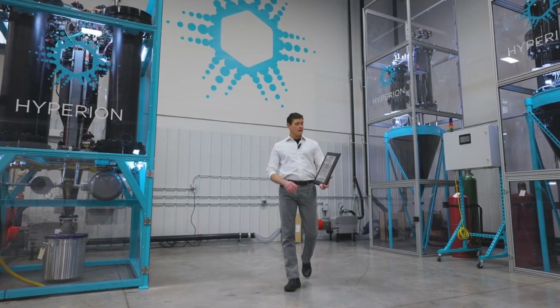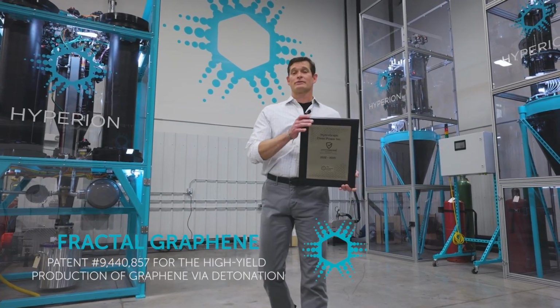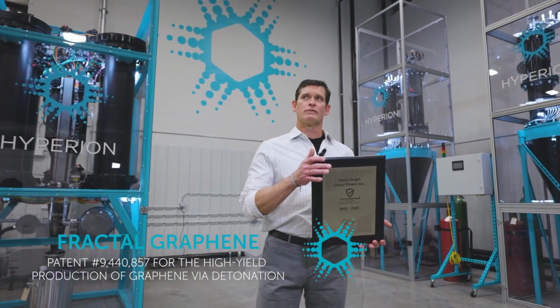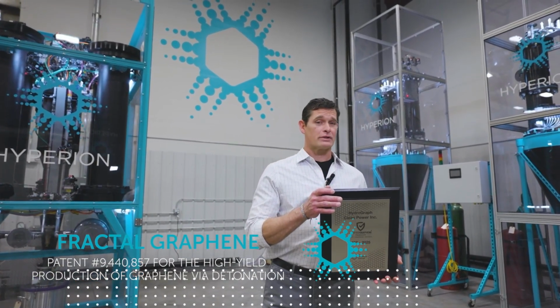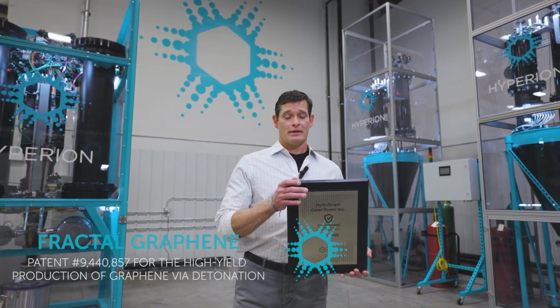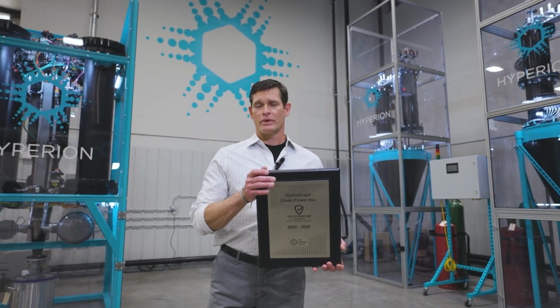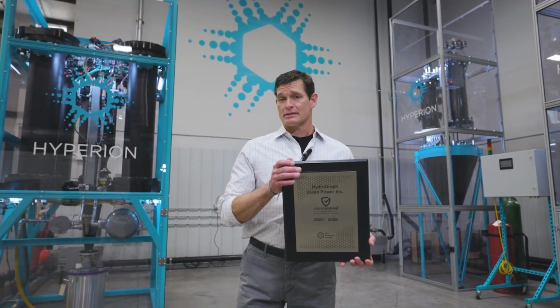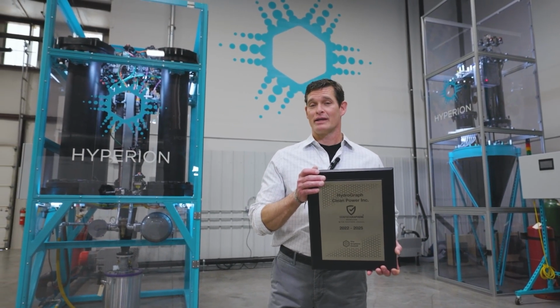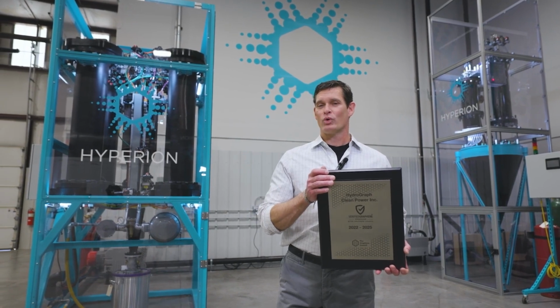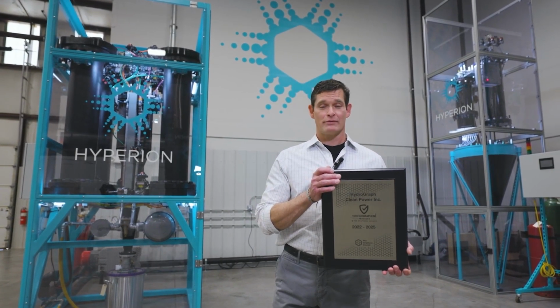HydroGraph's fractal graphene is certified by the Graphene Council as few layer, that's 2 to 10 layer, non-functionalized turbostratic graphene in a size of 20 to 50 nanometers. It has the highest consistency, and it sets the industry bar in purity at 99.8% pure carbon in the form of graphene.